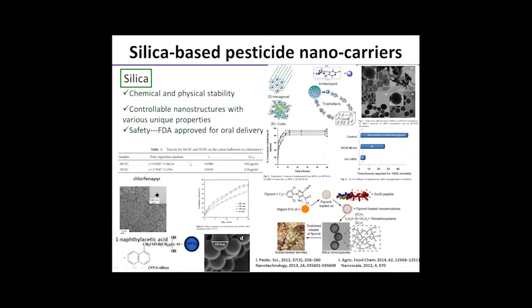Nanopesticide formulations using mesoporous silica monoliths and mesoporous nanoparticles as carriers have been recently reported. I have listed several examples here, all showing interesting sustained release properties and toxicity to target pests. This paper uses silica nanoparticles as a pesticide carrier, which shows good dispersity because the particle size of these nanoparticles is uniform and small, and also shows toxicity to cotton bollworm.